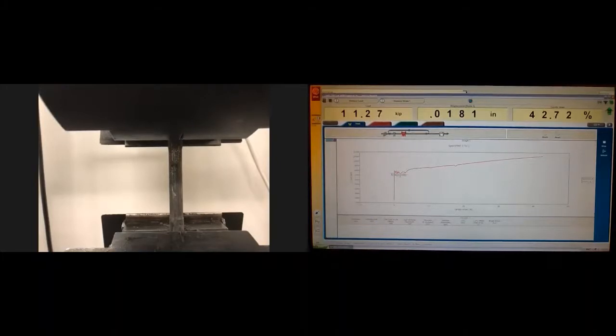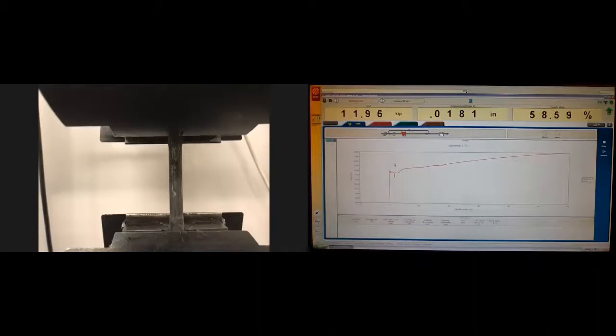And again, you see how yield strength can be increased. So moving from, or yield force, in this case, we don't have stress calculated yet, but force at the yield point. Now you see how it moved from this level to up here. So the change is substantial. And this is because this material, 1040 steel that contains 0.4% carbon, is capable of increasing strength due to deformation, since the carbon content is not so high as to increase the brittleness of the material, and at the same time it is sufficient for the strain hardening of this steel.